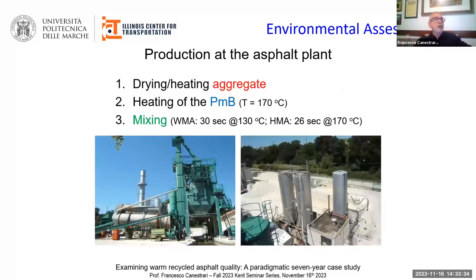In detail, we assumed three separate phases during the production at the asphalt plant: the drying and heating phase of the aggregates, the heating phase of polymer modified bitumen at 170 degrees C, and the mixing phase with different time and temperature for warm and hot mixtures.